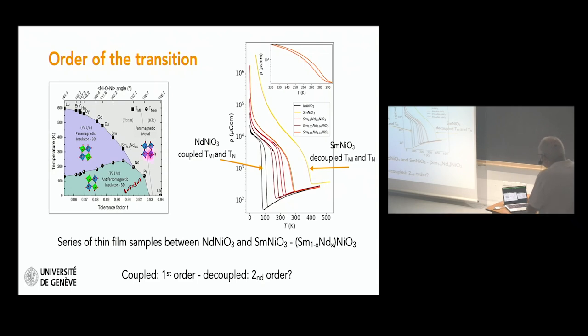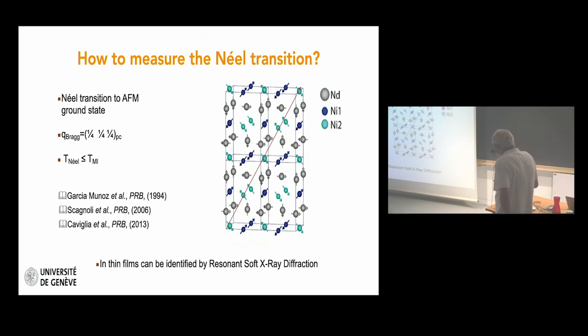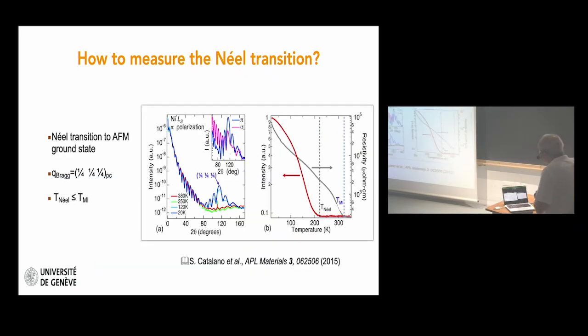And these solid solutions are shown on this graph. So 3 different samples, 1, 2, 3. These 3 samples display metal to insulator transition. They all display hysteresis. And the question now is, what is the magnetic transition temperature in this system? So what we did, we measured this magnetic transition, and the way you do this, you perform resonant soft X-ray diffraction at the nickel L edge, and you look for the long wavelengths, these 4 unit cell wavelengths of the magnetic order.